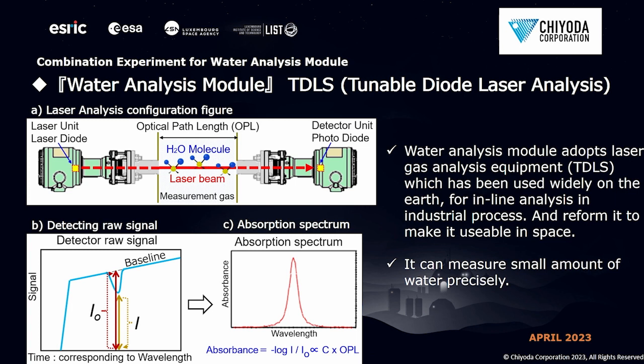And this TDLS measures the optical absorption in the near-infrared region, and it calculates the specific gas concentration from the area or the peak of the spectrum curve. There is almost no interference from transmitted light or other components, and it calculates precisely even under tough conditions. And we have tested to see whether this TDLS is compatible with the other parts of this module, and also to see the lower limit that this TDLS can measure.